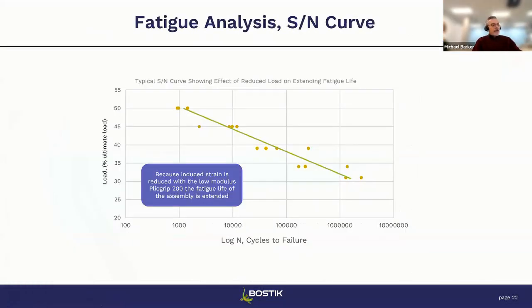So then what other advantages might be created with this low modulus adhesive? Well, as the part expands and contracts with temperature, it generates a certain strain on the bond line. With the low modulus adhesive, the stress on that bond line will actually be less. And as a result of a lower strain on the bond line, it translates into a higher fatigue resistance for the assembly. And that's a pretty significant point to take away.